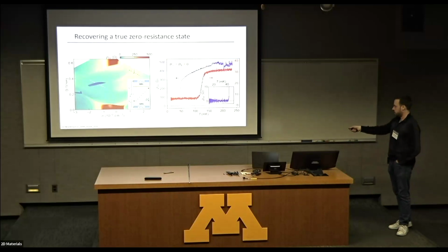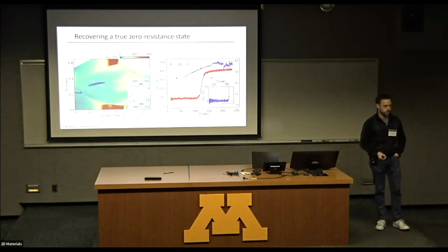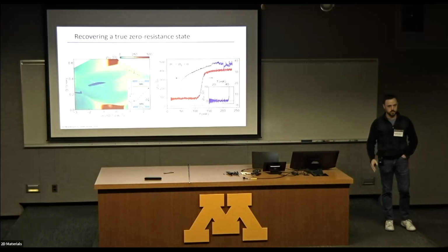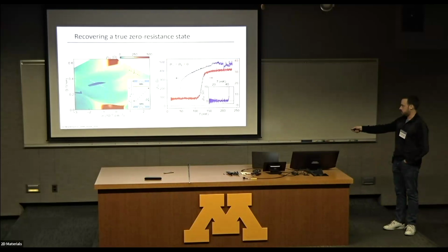So within our measurement noise floor of about 1 ohm, we see true 0. This is in Rxx; we also see 0 in Rxy, which I'll show you later, with a transition temperature of just below 50 millikelvin.